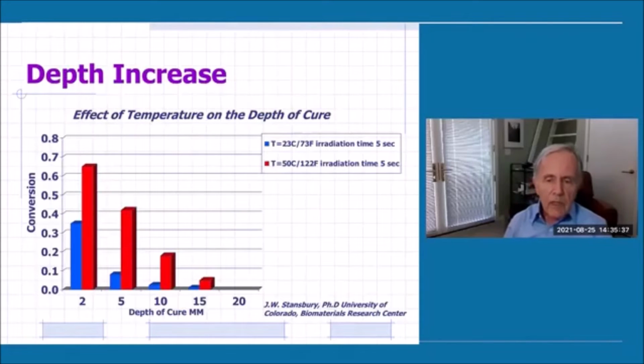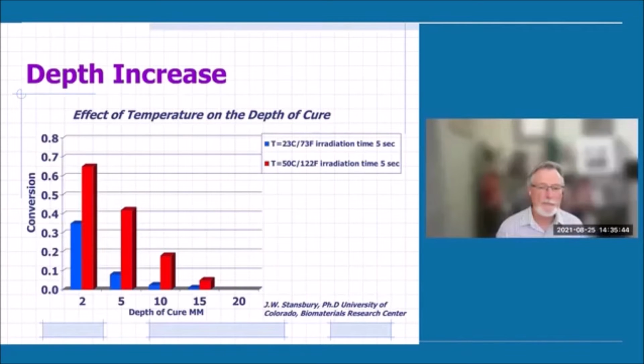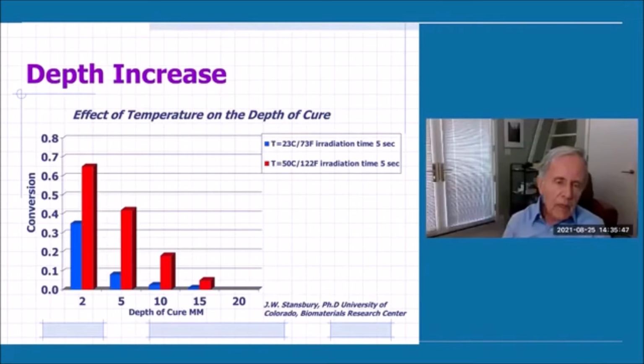This was a study by Dr. Stansbury at the University of Colorado. They used something called FTIR, a big name, Fourier transform spectroscopy. And they do that because it shows them the exact amount of conversion. They look at a computer screen and they see a curve that actually shows how much the material has been polymerized. So by using that technique and heating the materials, they found that both of these 2 advantages take place. A, you're curing deeper at that same high level of conversion, and you do it with increased temperature. So bottom line, increasing temperature increases conversion, and it increases depth of cure. And that's what we're seeing in this curve.